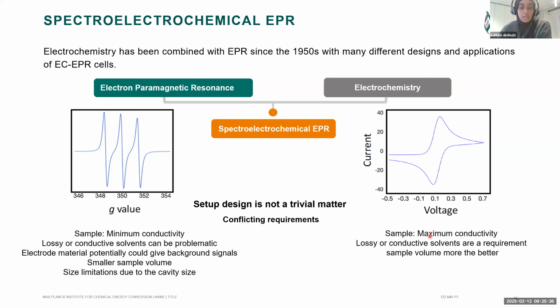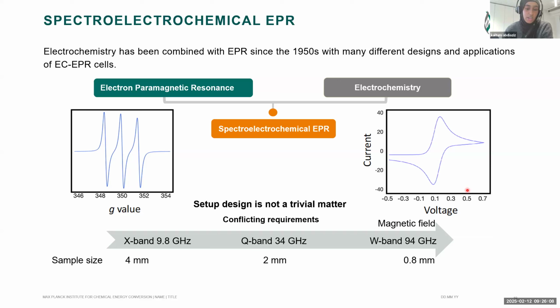Whereas in electrochemistry, conductivity is a requirement. So you need to minimize any resistance coming from a lack of conductivity. And so lossy and conductive solvents, so electrolytes or aqueous solutions, are a necessity. The sample volume in electrochemistry is typically in the milliliter range, whereas in EPR it's the microliter range. So that's another conflicting requirement, and it becomes more apparent when you go to higher frequencies. In X-band EPR, you have a 4 millimeter space in your EPR tube, and this gets significantly smaller the higher frequency you go. So you can imagine making a spectroelectrochemical setup at higher frequencies is very difficult.